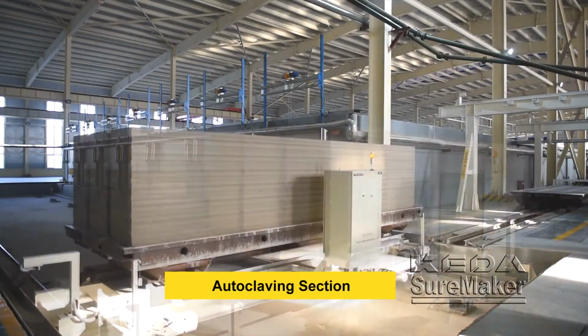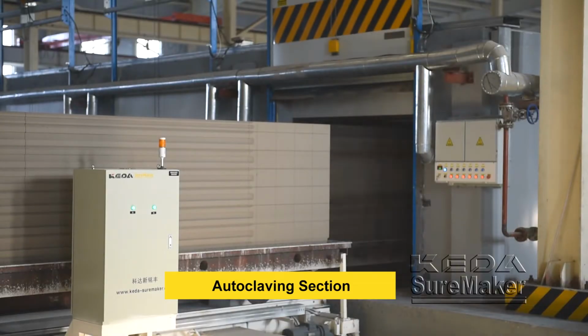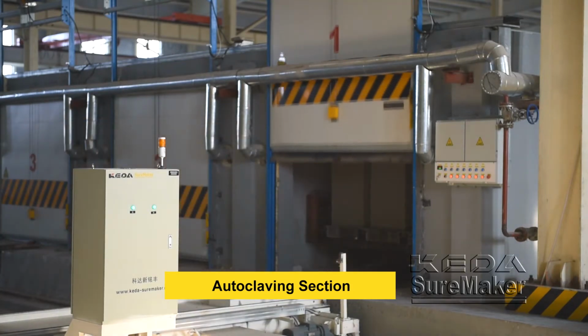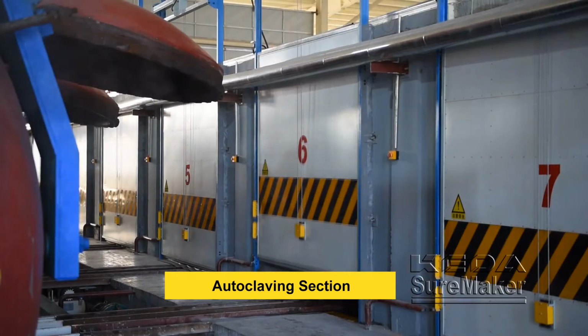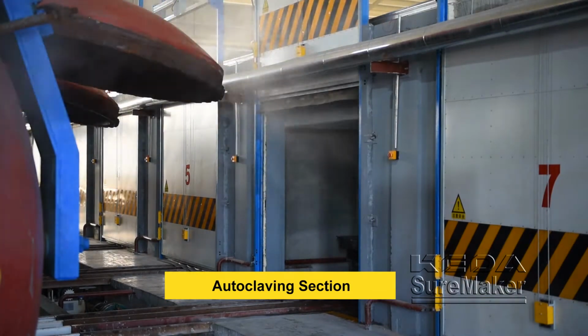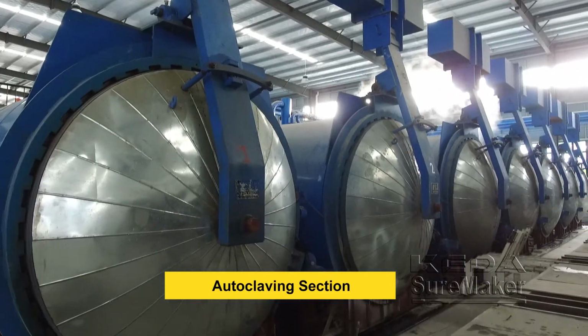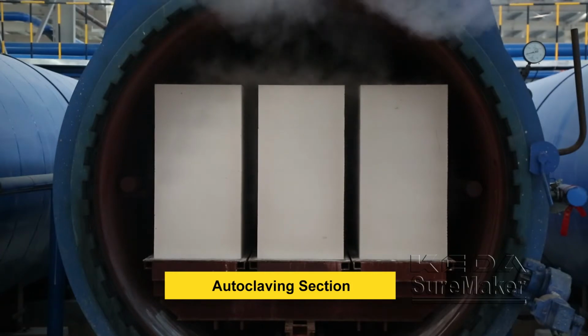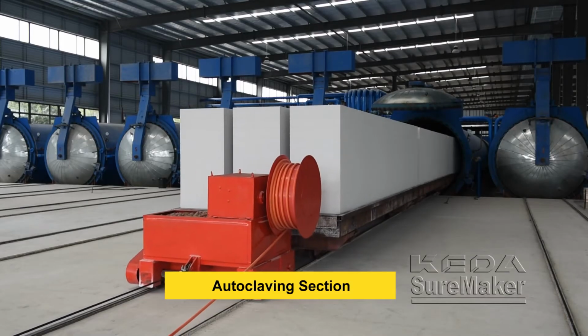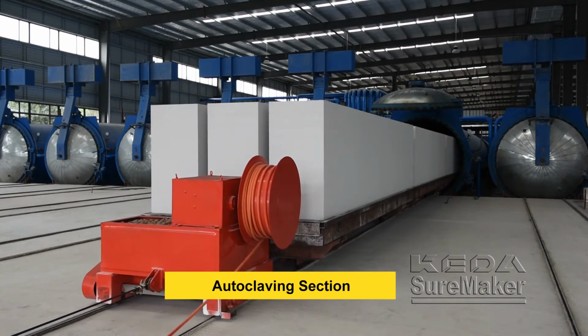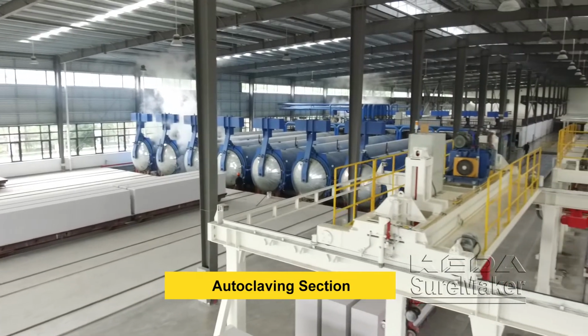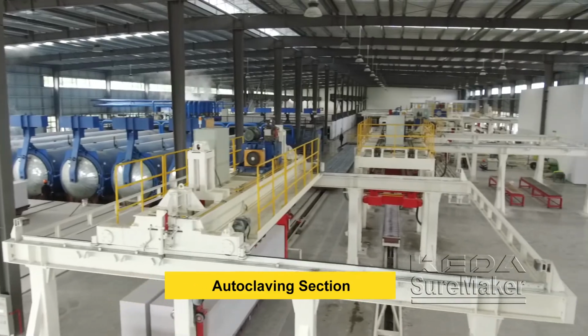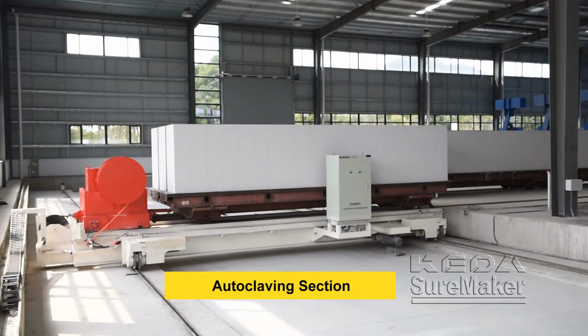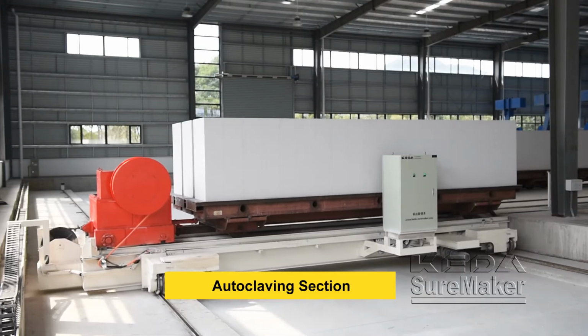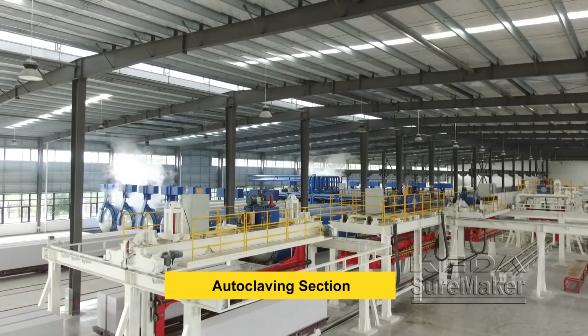The ferry car will take them for grouping before autoclaving. After grouping, 3 mold curing cars will be pushed into the autoclave for curing 10 to 12 hours under 200 degrees Celsius, 1.2 megapascal. Steam and autoclave can be reused from each other to save energy consumption. The curing car with white cakes goes to the packing area through the chain conveyor.